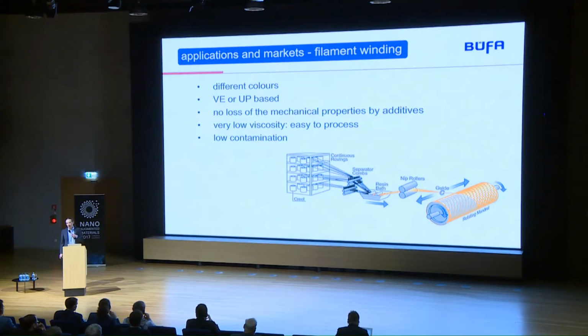We found no loss of the mechanical properties using additives. And also in this application, we have very low viscosity. This means easy to process, because this is a really quick process, and essential is that you need a fast impregnation of the roving. And also low contamination. These are really a high volume business, and normally the materials are in a storage tank, and if you use this storage tank with really black, carbon black material, you never use it for a transparent one, or you have to do a really hard and a lot of cleaning work.